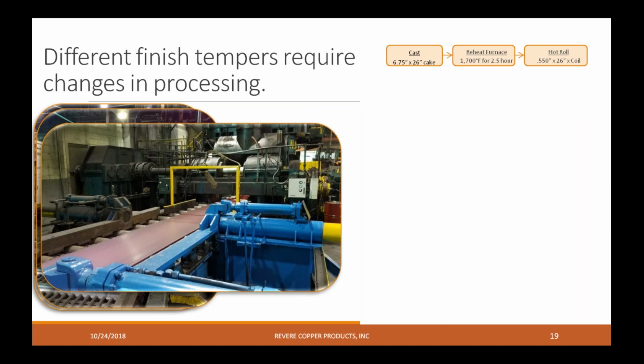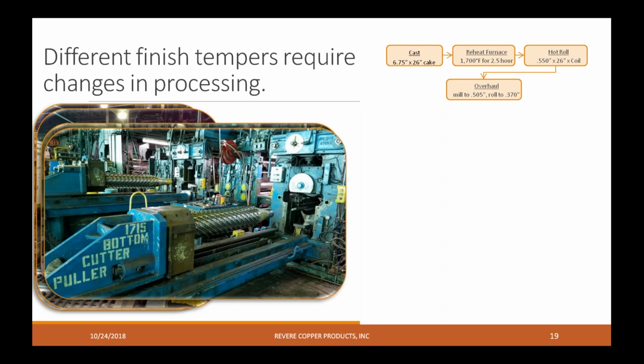The first step is an overhaul process, and that's because when you heat the metal, you get oxide. So those cakes were black. Once this coil is rolled at 1/2 inch thick, it will be black. It'll have oxide on both sides of it. So the first step is to remove that oxide. So that's milled. So it's physically scraped off and removed. So there isn't any squishing of the metal or cold work of the metal there. So again, you don't have any cold work between 0.550 and 0.505.